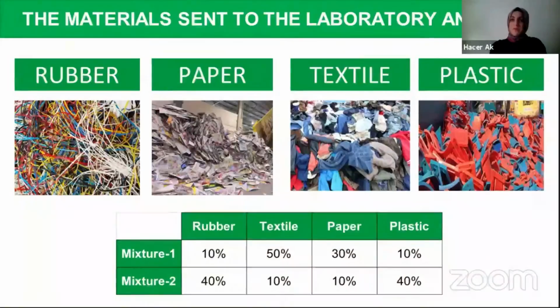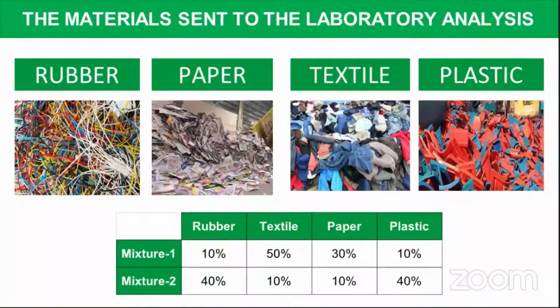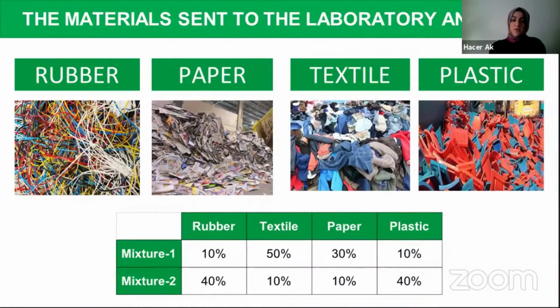We also generated 2 different mixtures to investigate the optimum RDF combination. The raw rubber, paper, textile, and plastic, along with 2 batches, were sent to the facility for analysis. 10% rubber, 50% textile, 30% paper, and 10% plastics were combined for the first batch, and 40% plastics, 10% paper, 10% textile, and 40% rubber were mixed for the second batch.